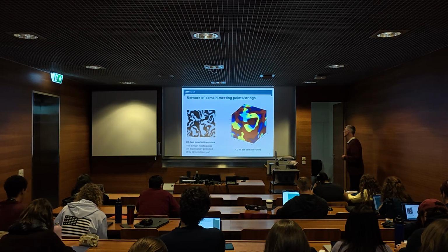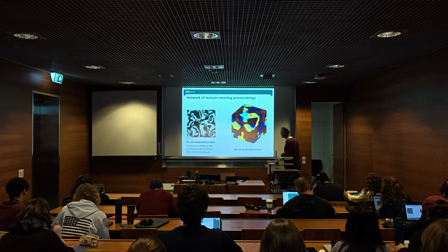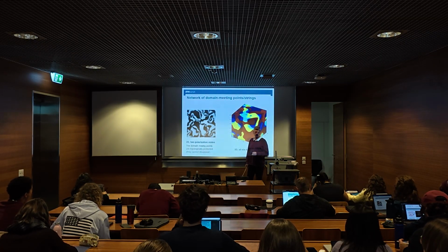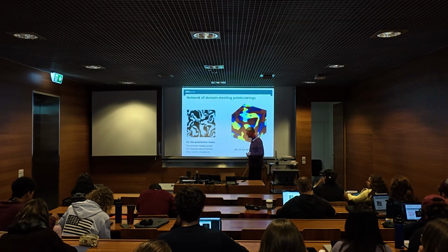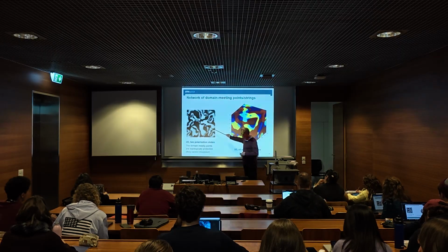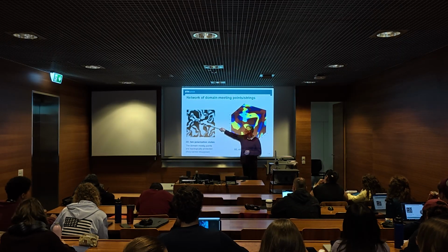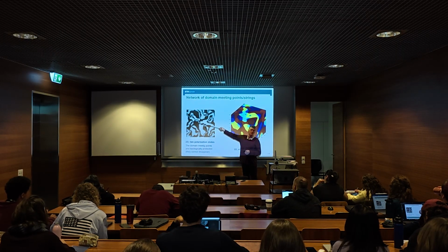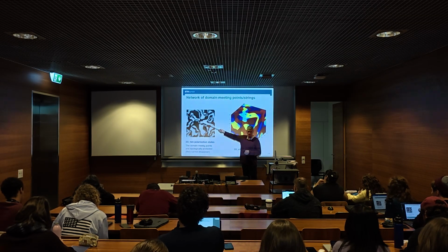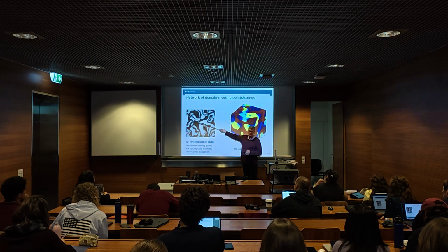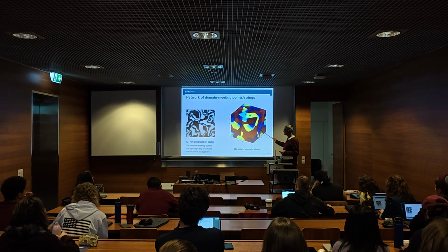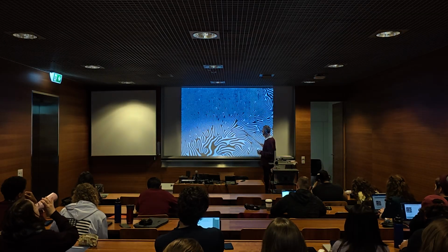Here is a little excursion further into it. This is just to tell you that very often there's much more out there than just saying, okay, I'm looking at ferroelectric domains. So when you have these meeting points of domains at the surface, then you have a spot where they all meet. And if you go into the bulk of the material, the spot will become a line, right? So here we see this computer simulation of these 6 domain states.